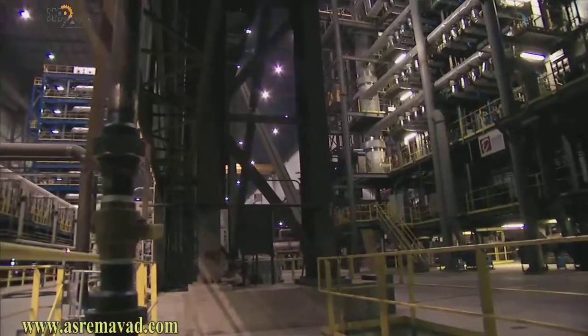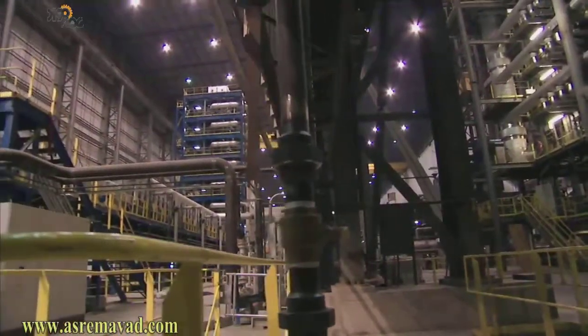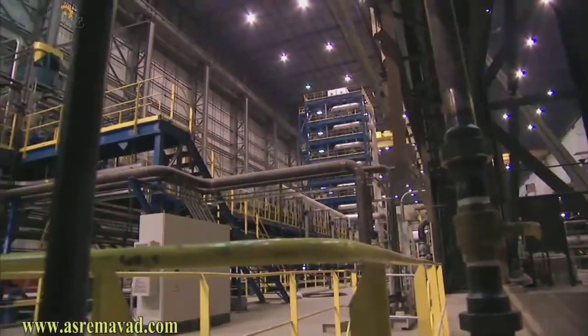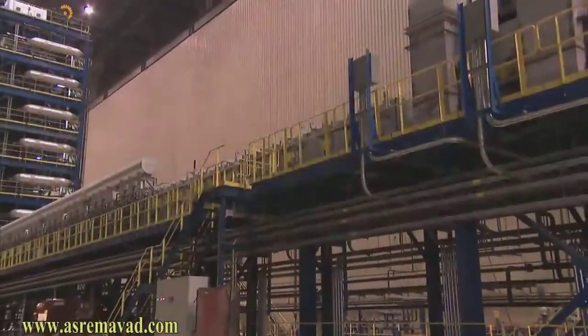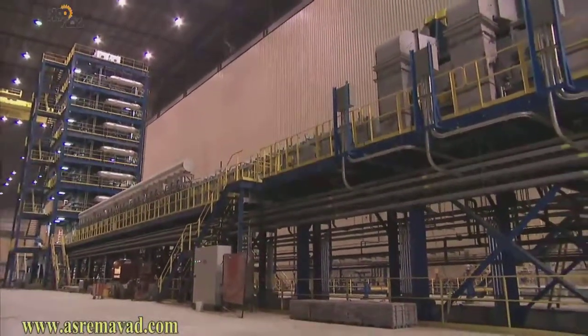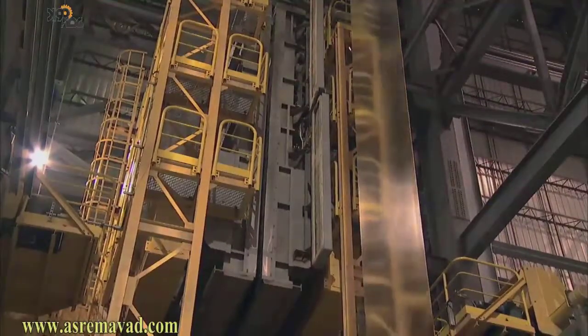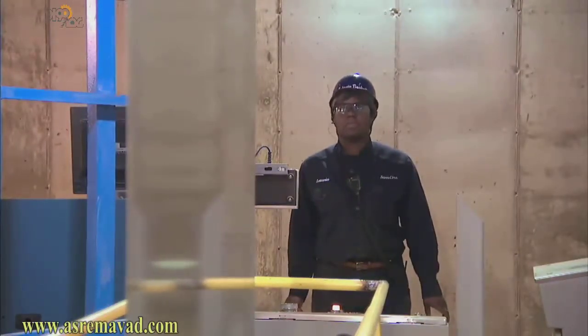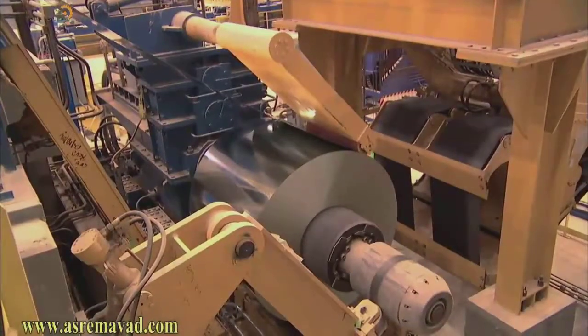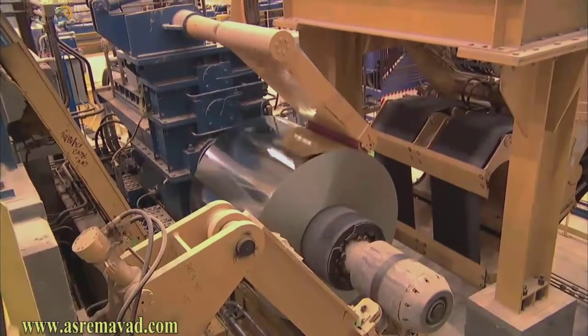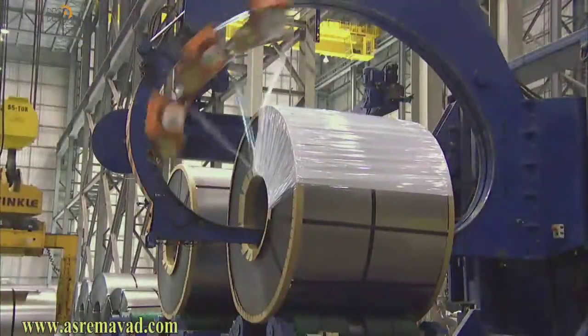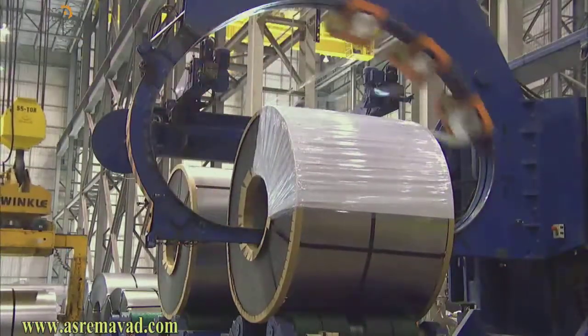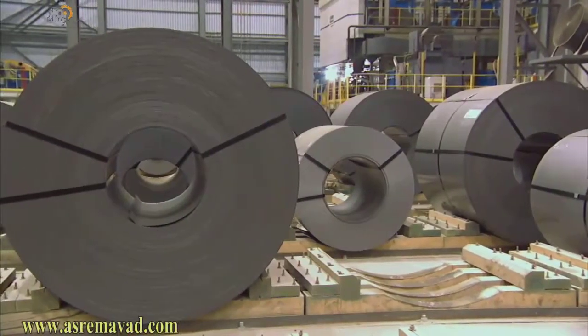Multiple hot-dipped galvanizing lines allow for improved scheduling and redundant capability, while further expanding product ranges from as light as 0.015 inches to as heavy as 0.130 in widths of 36 to 72 inches, with a wide range of coating weights. Automotive applications often require a galvanneal instead of galvanized coating. This process results in coatings which can be better formed, stamped, or bent, and which have a dull matte finish that allows for improved paintability. Typical applications for galvanized and galvannealed coils are any corrosion-resistant applications, including building panels, HVAC, household appliances, grain bins, automotive bodies, and other outdoor applications.